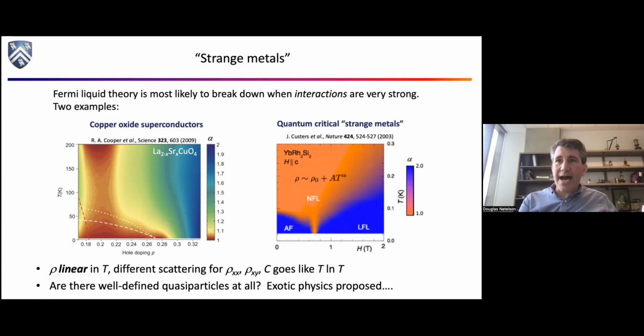Who cares? Well, it turns out that if you turn the theorists loose on this, they will tell you this has really deep ramifications. It implies that this whole picture of quasiparticles, of well-defined, charge minus e, spin one-half things bopping around, potentially falls apart in the strange metal case, because you just can't get linear in T resistivity from that, right? So something very peculiar is going on.